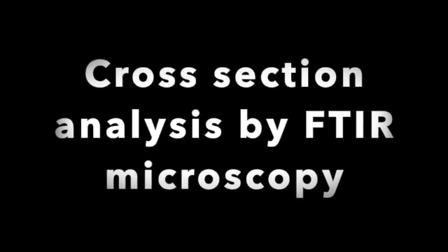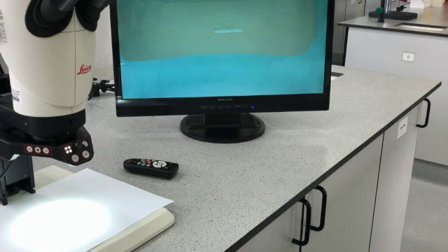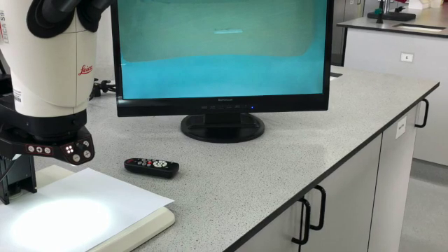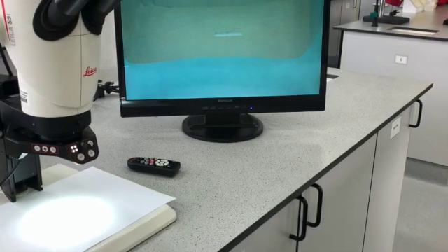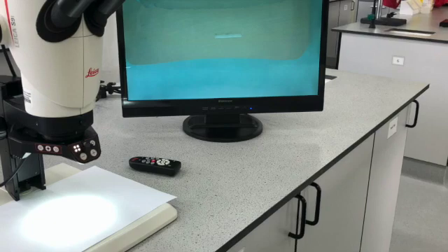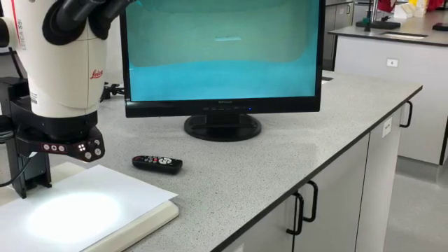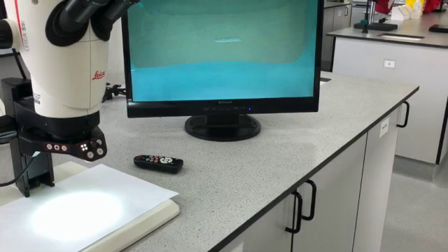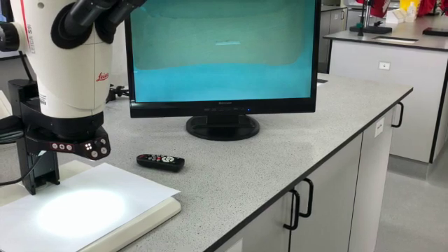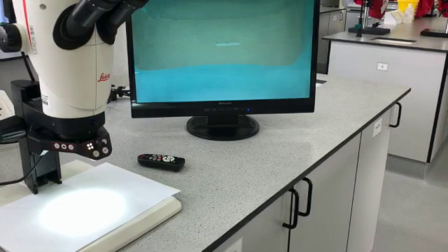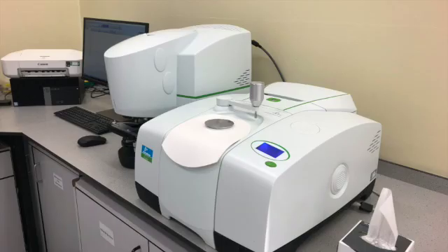For cross-section analysis by FTIR microscopy, first we look at the cross-section under the low-powered microscope, and you can see here on the screen where the adhesive has sandwiched the small paint chip in between the two layers. Now you can see the paint sample right in the middle, the white area, and what we will do is check that the paint sample is present there first, and then we will apply it to the FTIR